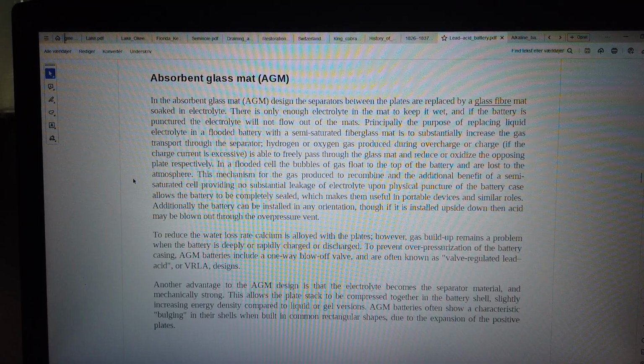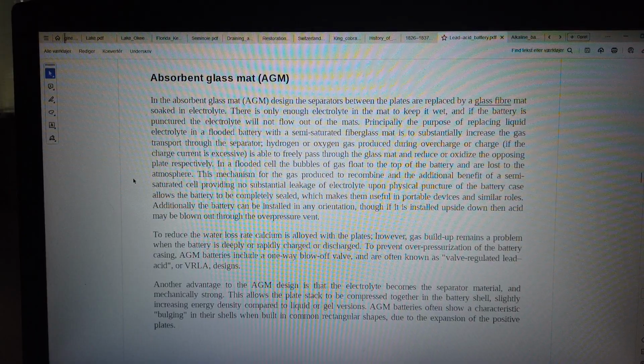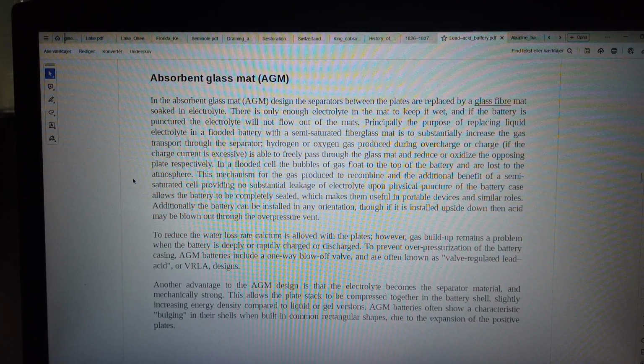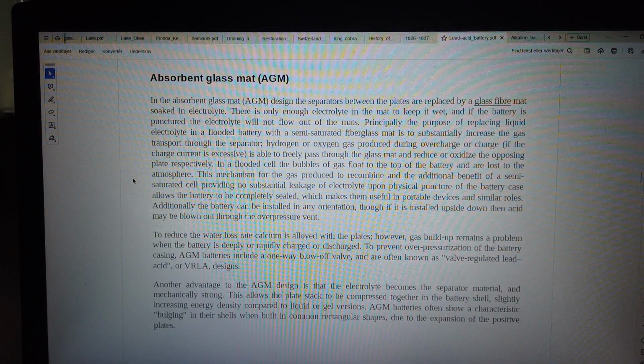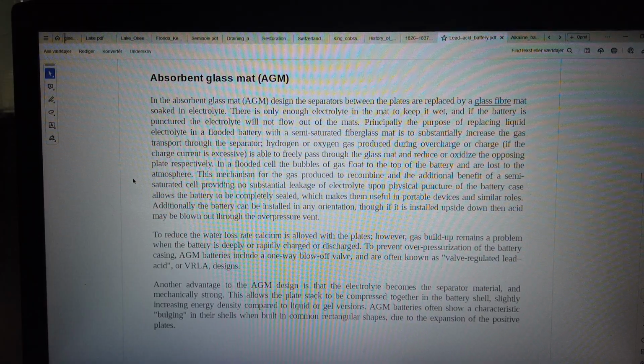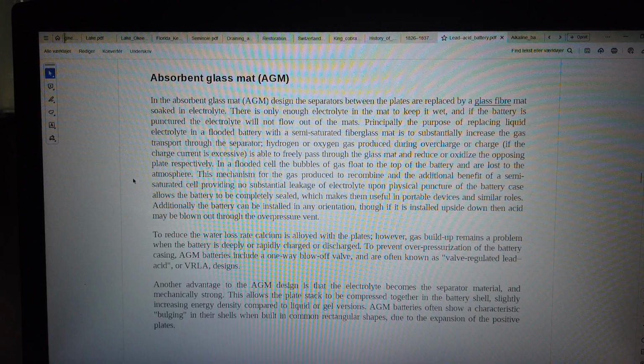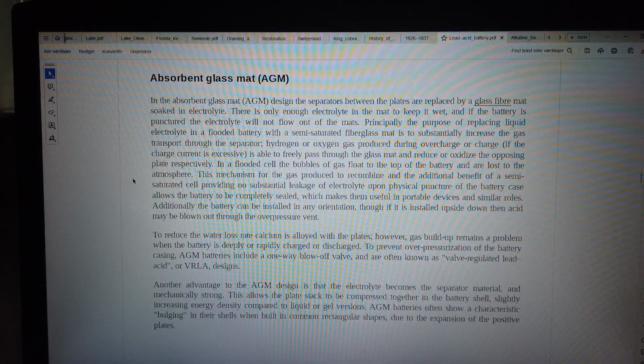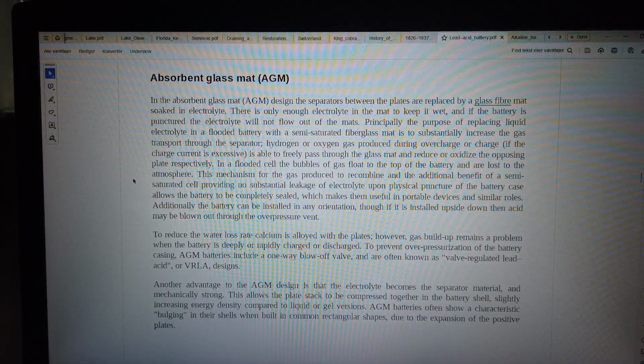To reduce the water loss rate, calcium is alloyed with the plates. However, gas buildup remains a problem when the battery is deeply or rapidly charged or discharged. To prevent overpressurization of the battery casing, AGM batteries include a one-way blow-off valve, and are often known as valve-regulated lead acid, or VRLA, designs. Another advantage to the AGM design is that the electrolyte becomes the separator material, and is mechanically strong. This allows the plate stack to be compressed together in the battery shell, slightly increasing energy density compared to liquid or gel versions. AGM batteries often show a characteristic bulging in their shells when built in common rectangular shapes, due to the expansion of the positive plates.